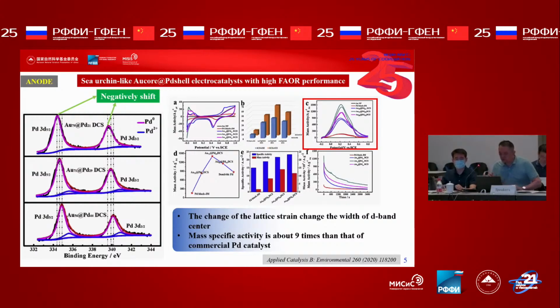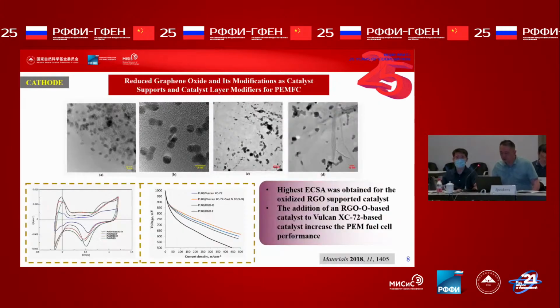The enhanced catalyst performance is probably due to the balance between the increase of the palladium lattice and the surface electron density, as shown in this picture. And for the low platinum loading cathode catalyst, we have prepared reduced graphene oxide, called RGO, and use it as support. The platinum nanoparticles were deposited on these materials and also on the Vulcan XC-72 carbon black, respectively.